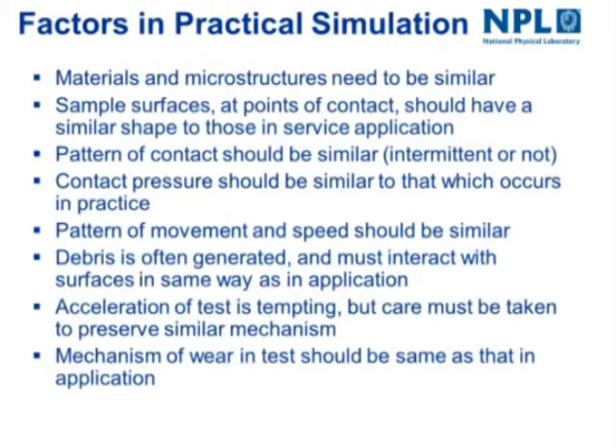So what are the factors in practical simulation of a wear test, a friction test? This is a little bit daunting, in fact, but you do need to consider a lot of these aspects, and the list is actually longer than this. So you need the microstructure and materials to be similar. The sample surfaces at the points of contact should have a similar shape to those in the application. The pattern of contact should be similar, intermittent or not. The contact pressure should be similar to that which occurs in practice. The pattern of movement and speed should be similar.